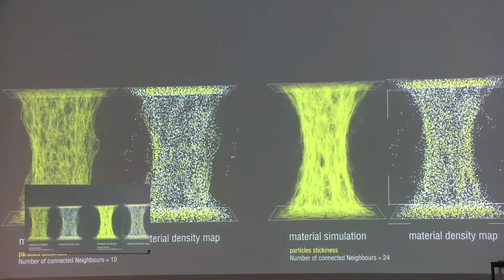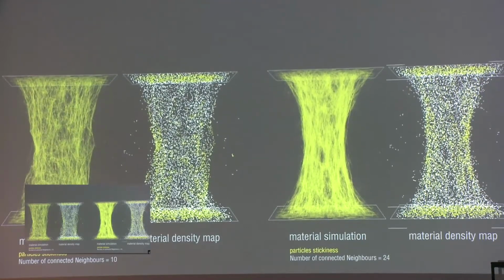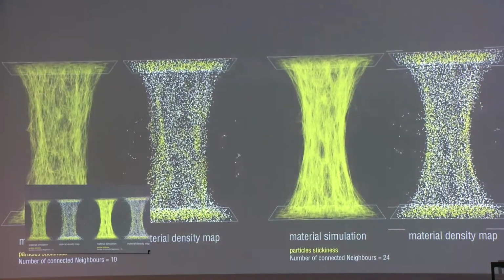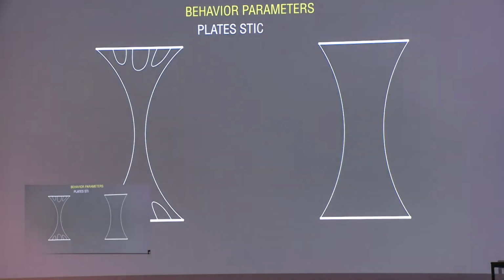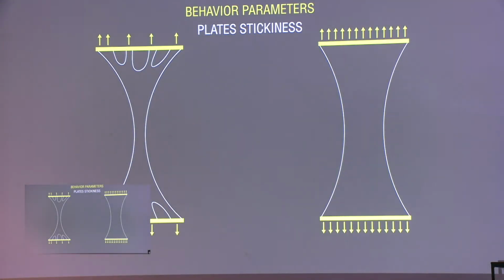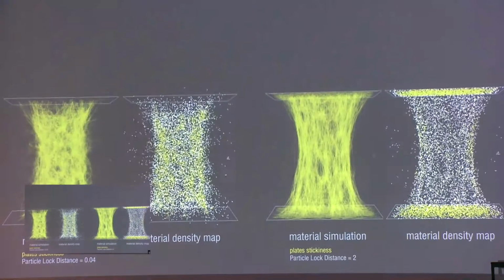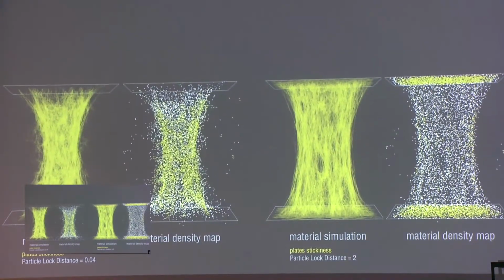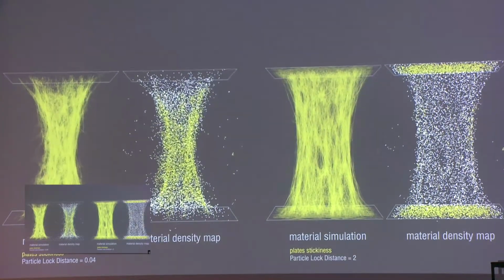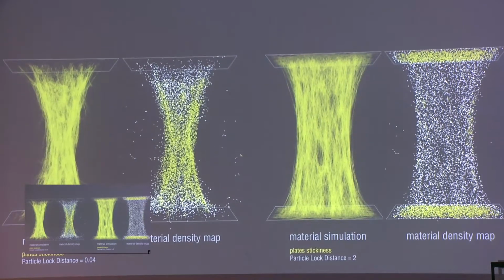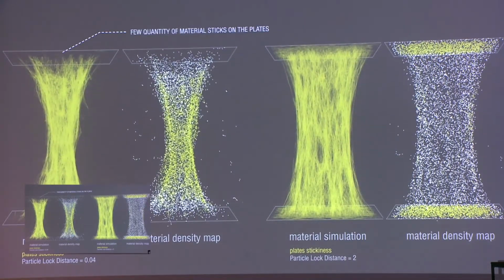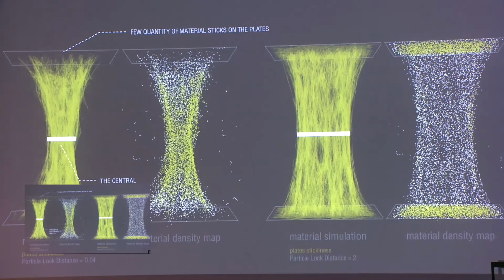The first parameter that we studied is the particles stickiness. So the number of neighbors that are connecting to each other are able to control and determine the section. Another important parameter is the plates stickiness. According to how much material sticks on the plate, we can have a big section or a small section. So we understood by this that the plates can change the structural behavior of our beams.